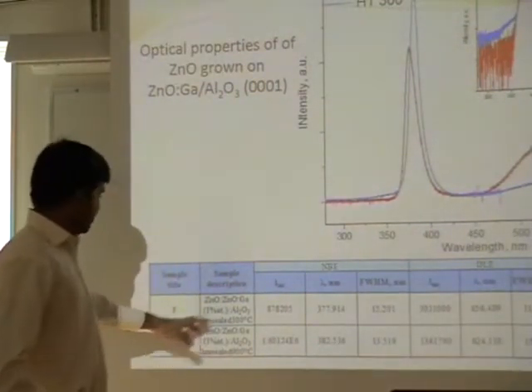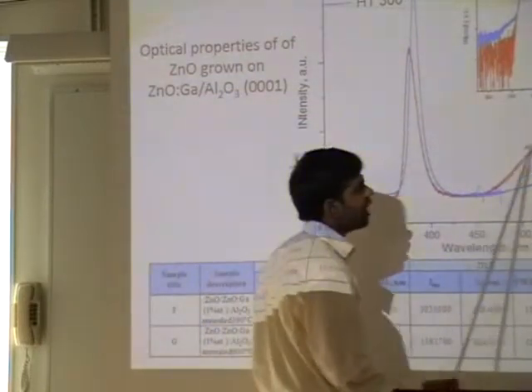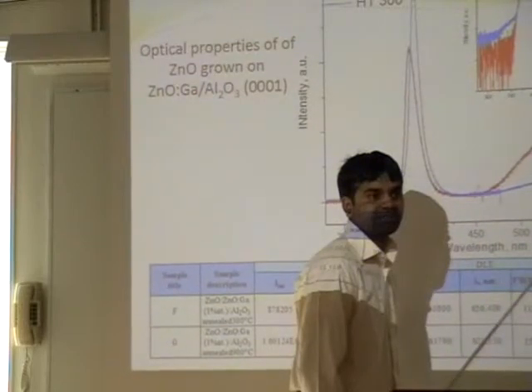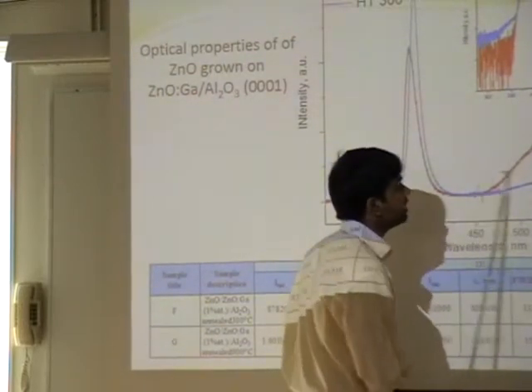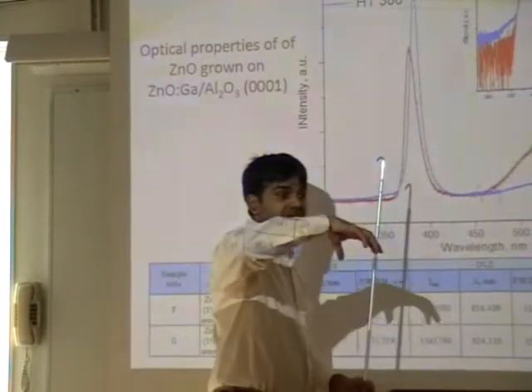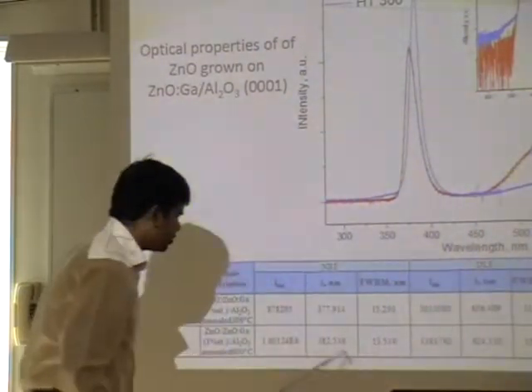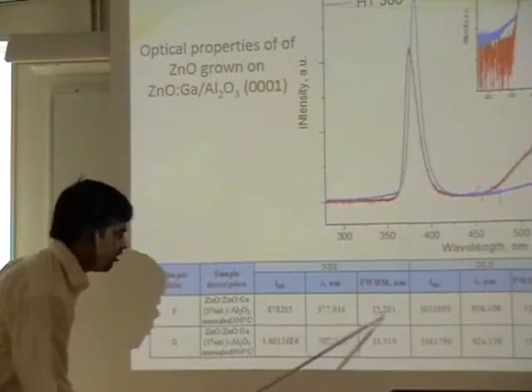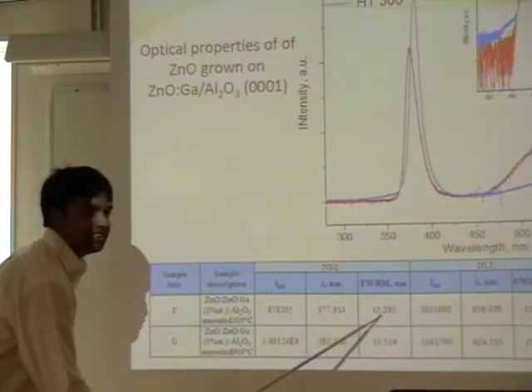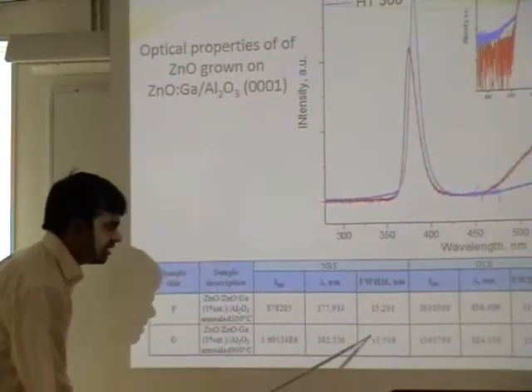Here when annealing at 900 degrees centigrade, a sharp increase of deep level emission. I told you, deep level emission is due to the impurity and defect. It means annealing has more effect on the optical property. Here, although a little bit of change in full width half maximum, which was annealed at 300, full width half maximum 15s, but with annealing they become a little bit smaller, not so much change.